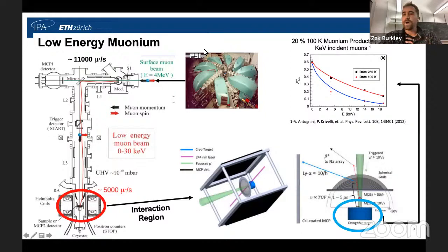So requirement number 1, low energy muonium that comes out at cold temperatures. How this is created is we take the proton cyclotron at PSI, and there's some pions that come from this, and we can get a surface muon beam from these pions. And then this goes into a noble gas moderator. And here we can get a low energy muon beam tunable between 0 and 30 keV. It comes down a beamline into this red interaction region. And this is where I would like to focus for today.